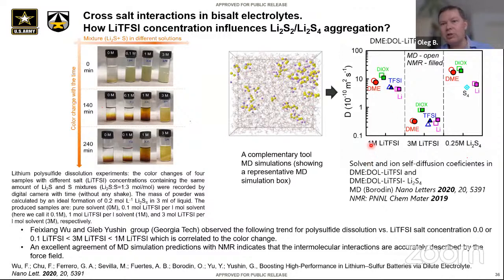And what I'm showing here is 1 molar lithium TFSI. MD results are open symbols, and experimental symbols are filled. I was very pleased with this agreement. Even when we went to high concentration lithium TFSI, both species diffused accurately, and they also had data for lithium in a mixture of Li2S4. And why I think that's important, in DME dioxolane, is that there is an excellent agreement here.